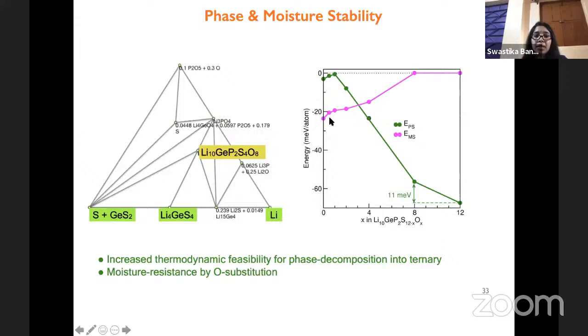So you see the phase diagram, the LGPS stands in a very safe position where it's a stable compound. The LGPSO, sorry, not LGPS. So LGPSO is a stable composition here. So increased thermodynamic feasibility is observed, and the phase decomposition, if you look at the right hand curve, is actually getting lower and lower. That says this is getting destabilized in some terms of the decomposition. However, the moisture stability increases.